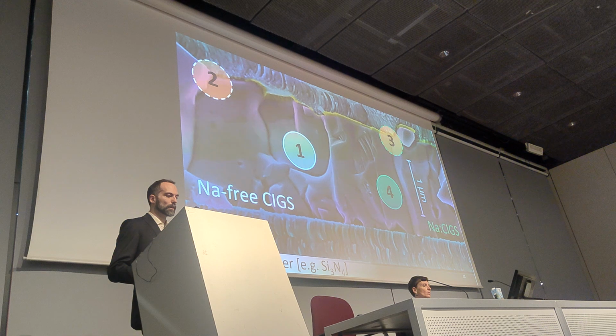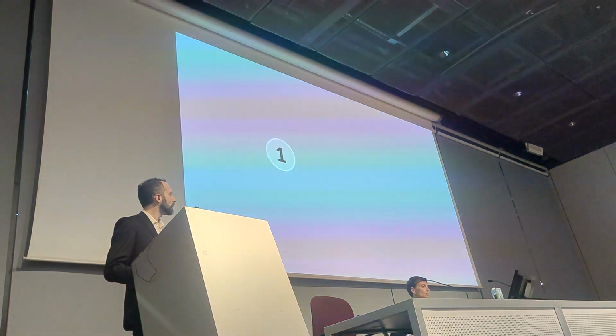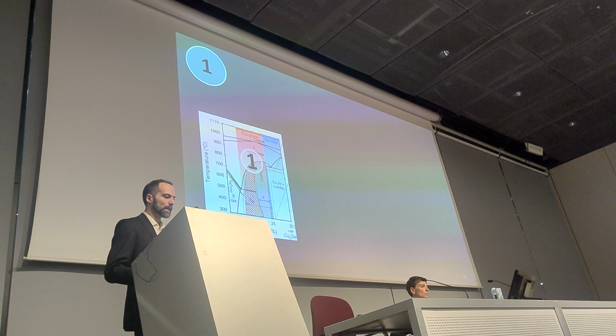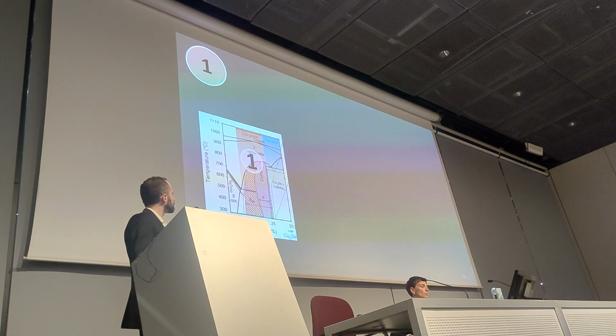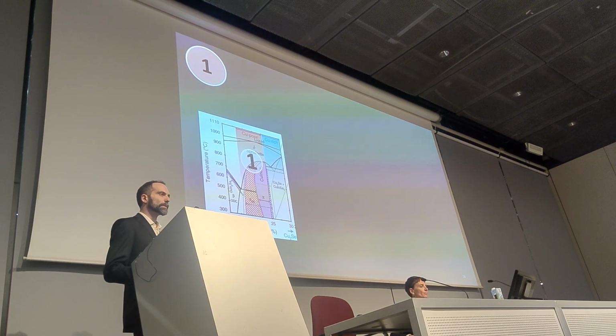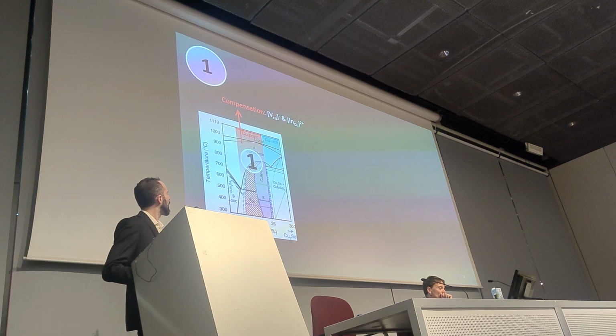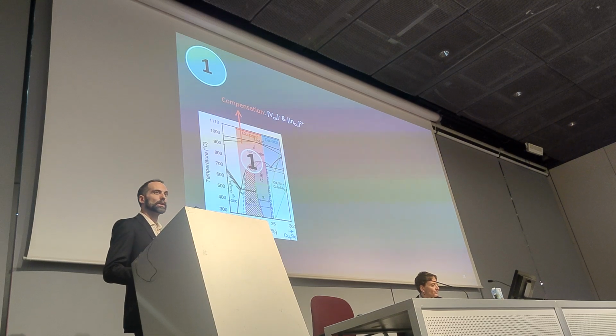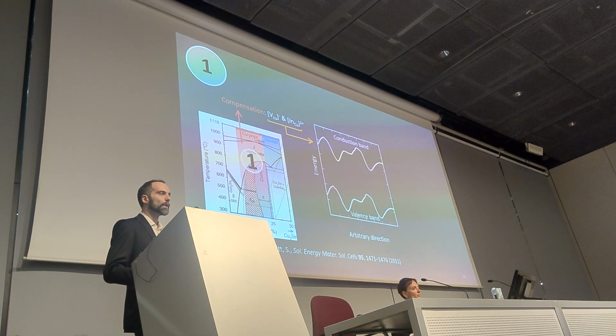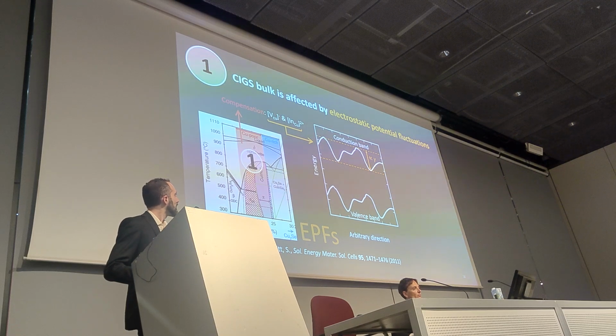So we're now going to look back into the bulk properties, because we have to highlight one important feature of this material. We've seen we grow the material copper poor, and this gives the best performance. But if you grow the material copper poor, there is an important consequence. We are deviating from stoichiometry. That means we have tons of point defects to compensate for the deviation. Specifically, what we have is vacancy of copper acceptors and indium copper donors. And these are point charge defects. And if they are not distributed equally within our material, what we end up with is electrostatic potential fluctuations that are nothing but a distortion of the band structure of the material.